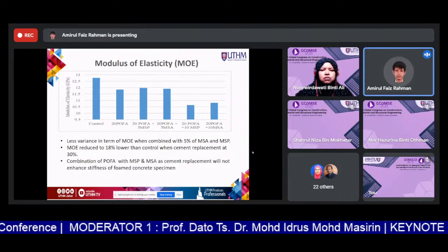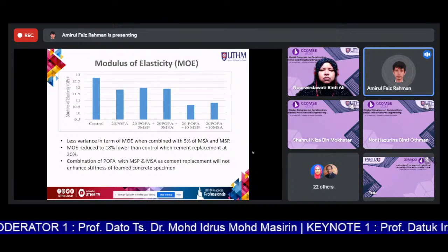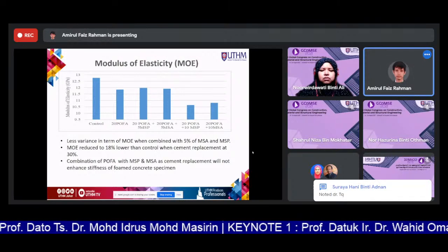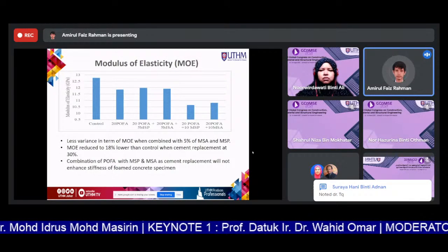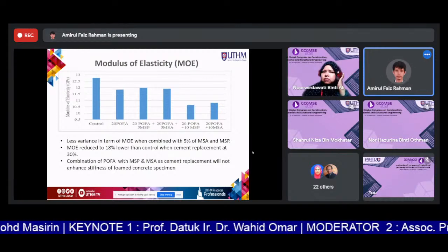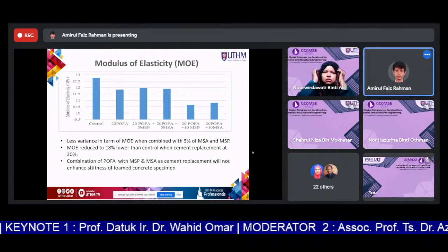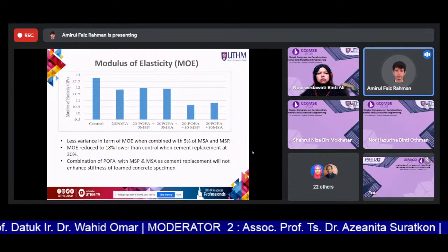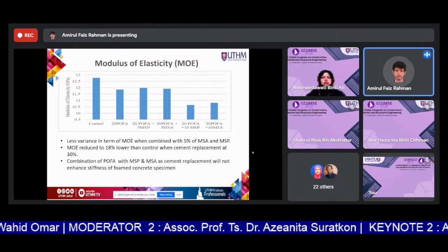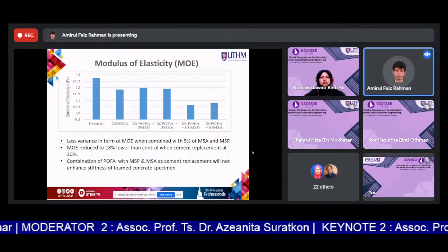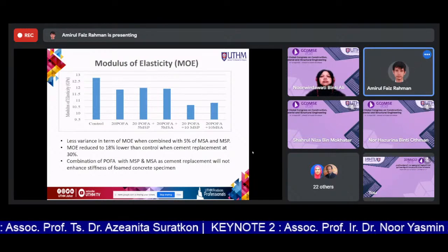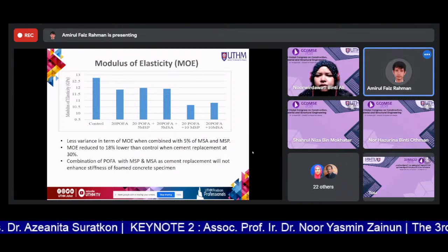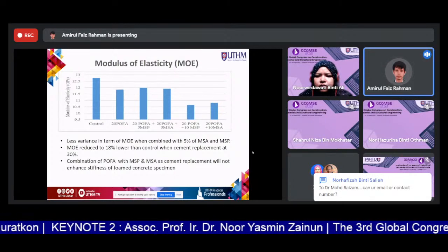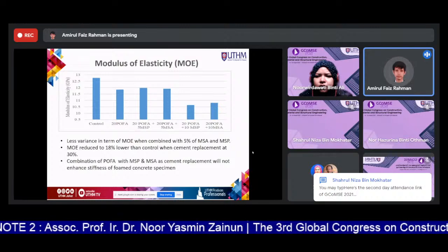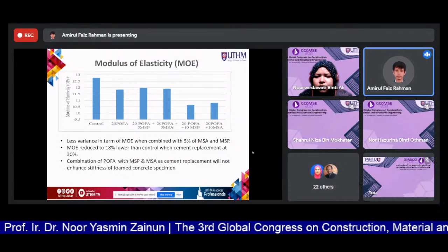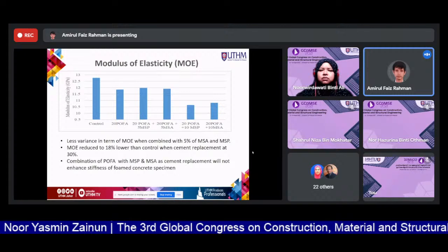And then for the modulus of elasticity, there is less variance in terms of MOE when combined with POFA at 5%. And then the MOE reduced by up to 18% when the cement replacement materials went up to 30%. And from the result, it can be said that a combination of POFA with both MSP and MSA as cement replacement will not enhance stiffness in foam concrete specimens.